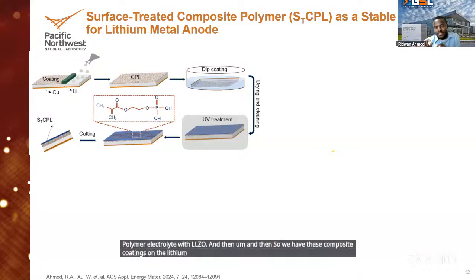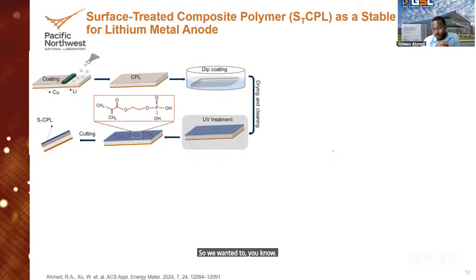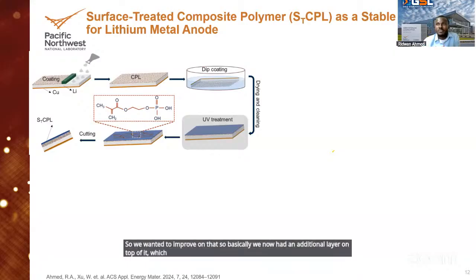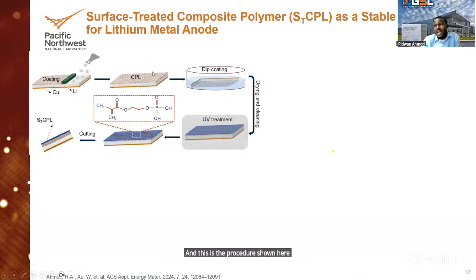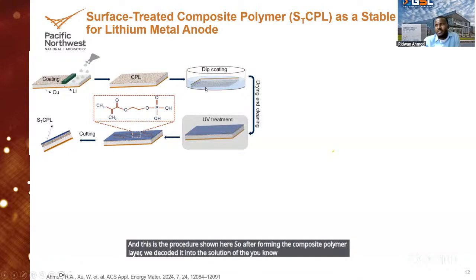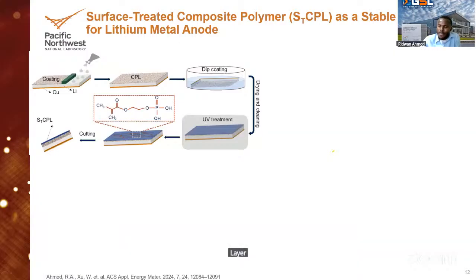And after that, because this PEO also has some issues, the chemical stability against some of the electrolyte we use is not as good, we wanted to improve on that. So basically, we now had an additional layer on top of it, which was some kind of surface treatment. That's why we call it surface treated composite polymer electrolyte. And this is the procedure shown here. After forming the composite polymer layer, we coated it into the solution we use for the surface treatment. After that, we treat it with UV light, and we have this layer on top of the lithium.